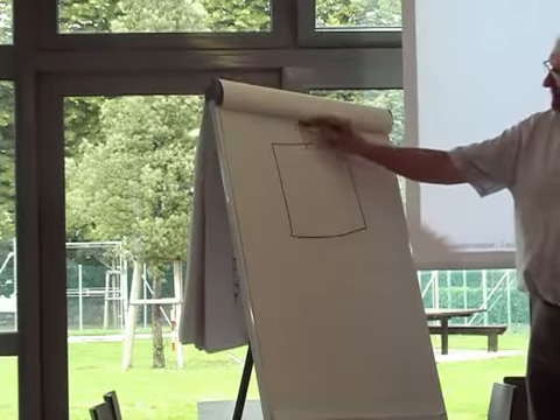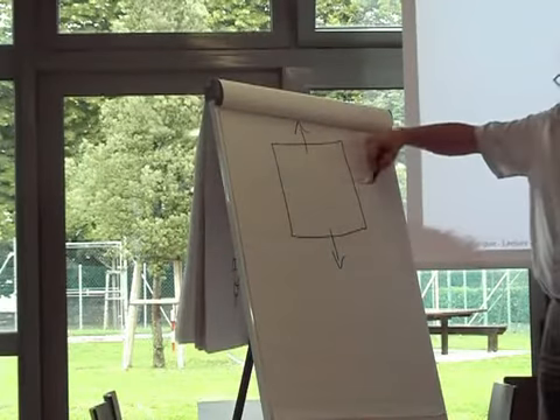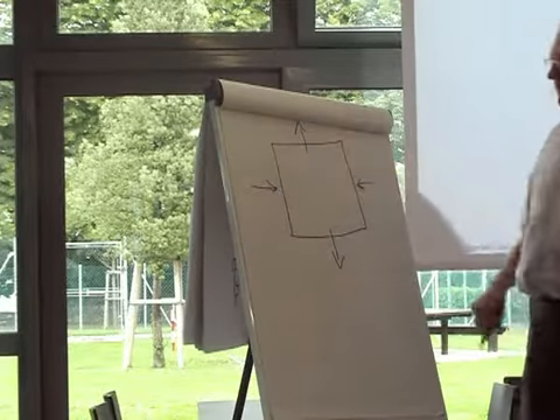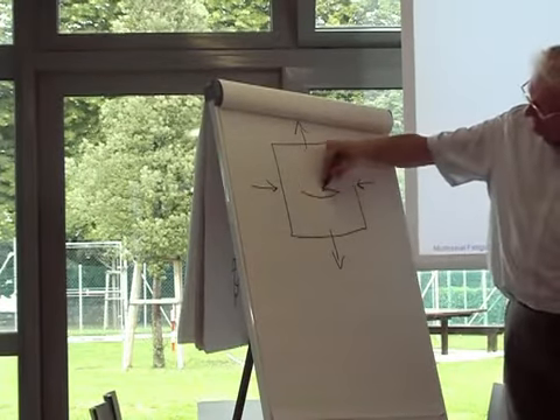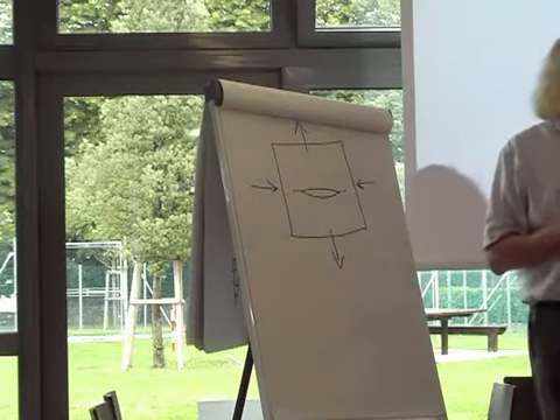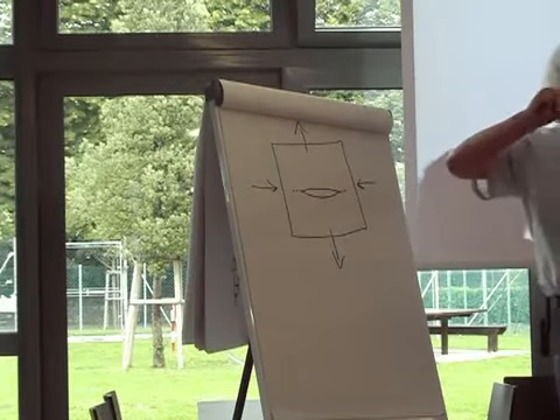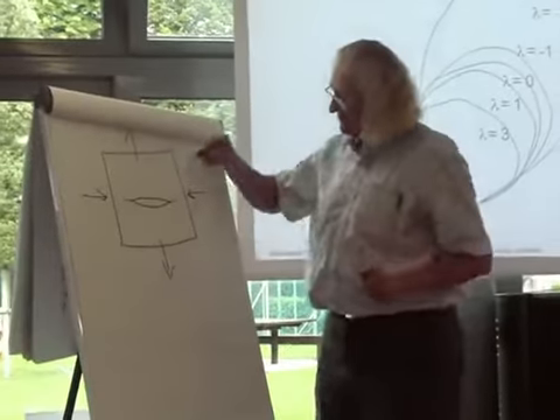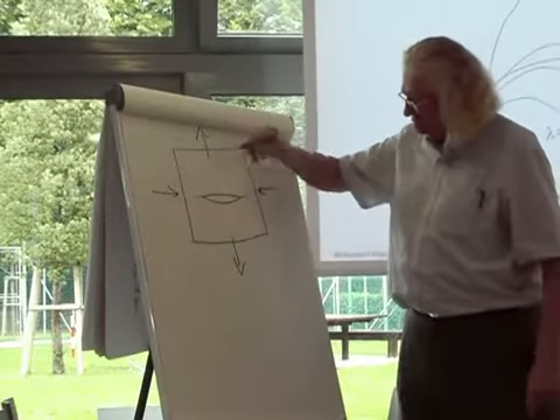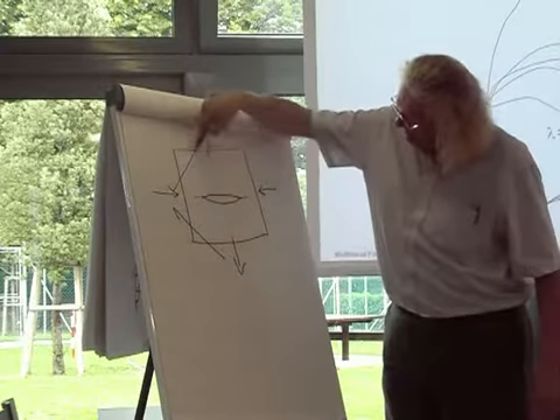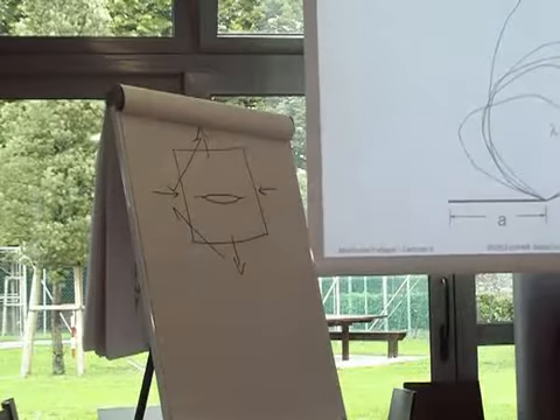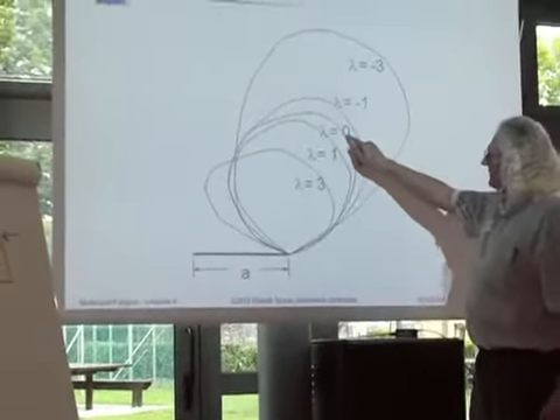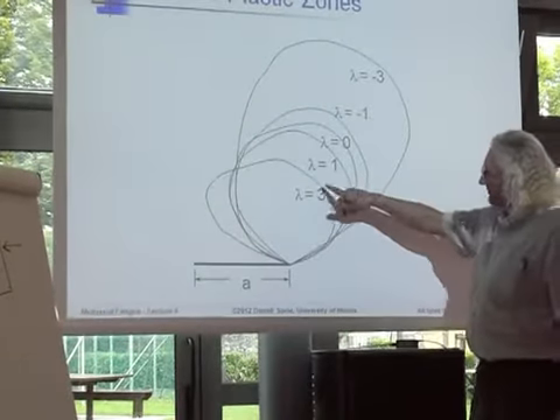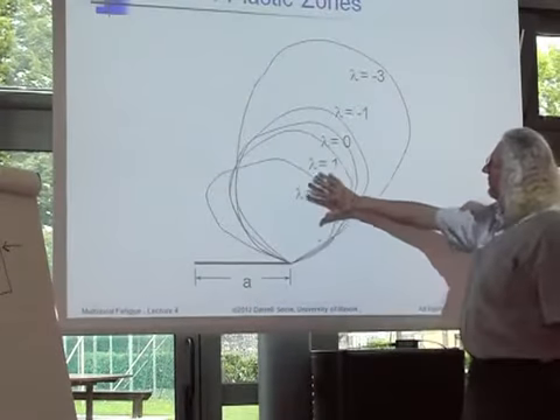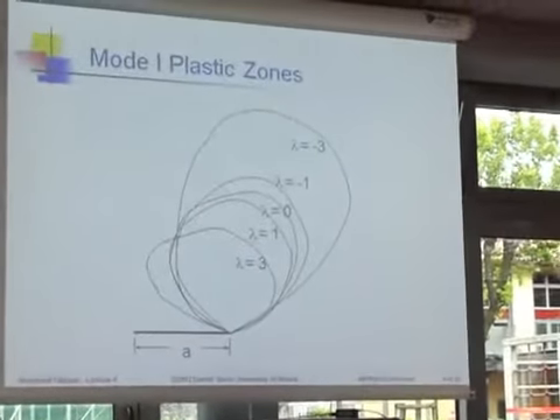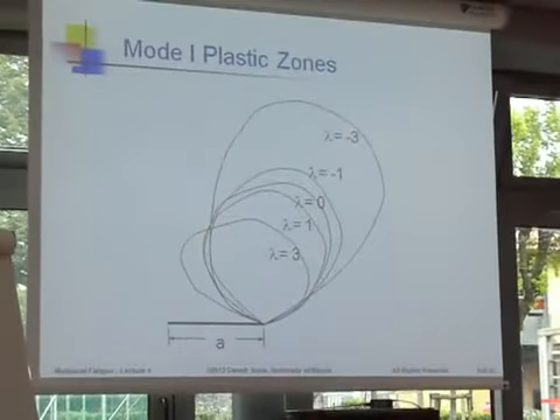So I have this load, and I have a principal stress that's here, and I have another principal stress that's here. And this crack is growing along this plane in mode 1. It's different than a shear crack growing in torsion. Right? This is really torsional loading. If I twist this, I'm really shearing this across this way. Okay? And that's, of course, when lambda is equal to -1. There's lambda is equal to 0, and lambda is equal to +3, right there. So plastic zone grows as you add the second component inside. And I will contrast that in a minute, what happens with mode 2.